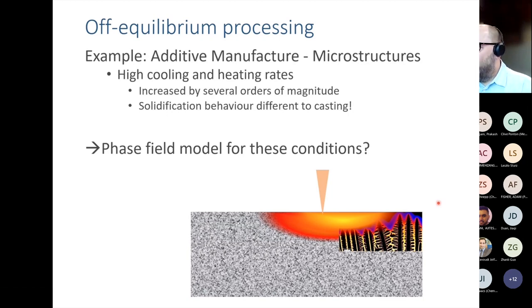But a number of processes have become very, very popular where that's not the case. For example, additive manufacturing now uses cooling rates that in the 90s and before were exclusively achievable in rapid solidification experiments at lab scale and in lab settings. And there it's been shown that we deviate from local equilibrium. We have partitioning of alloying elements that doesn't follow the phase diagram, but gets swallowed up by the growing solid during solidification at a much, much higher rate than we would see in a normal casting process. So the interface is out of equilibrium. So we're looking at off-equilibrium processing.